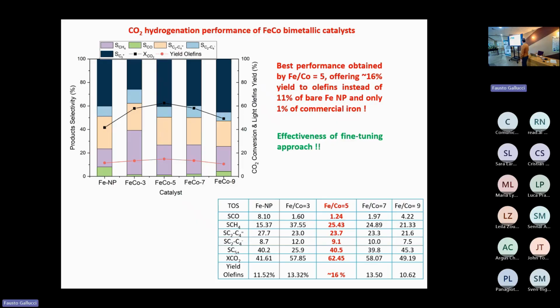And here we can see the CO2 hydrogenation performance of bimetallic catalysts of different cobalt iron ratio in direct comparison with the single iron nanoparticles. As you can see, the optimum performance is observed for this ratio, resulting in a yield to olefins of about 16% instead of 11% over single iron nanoparticles and only 1% over iron commercial sample. Thus, we managed to increase the yield to olefins from 1% to 16% over the same material, iron.